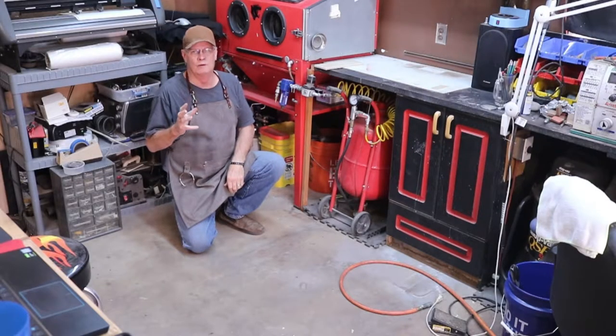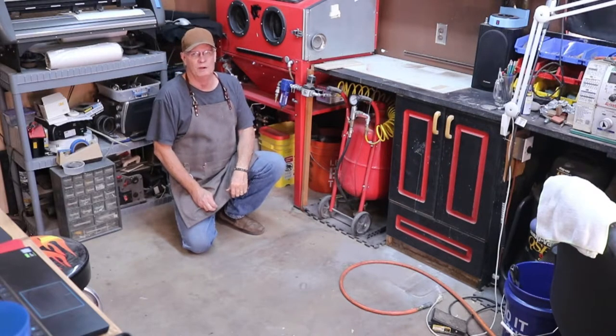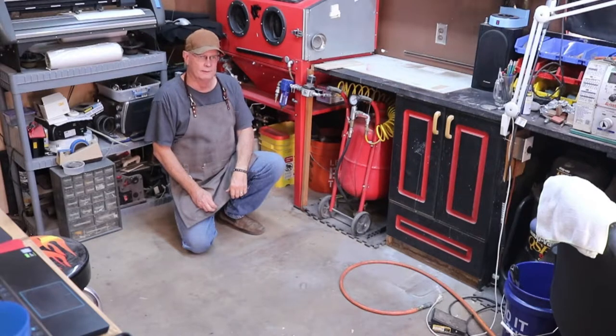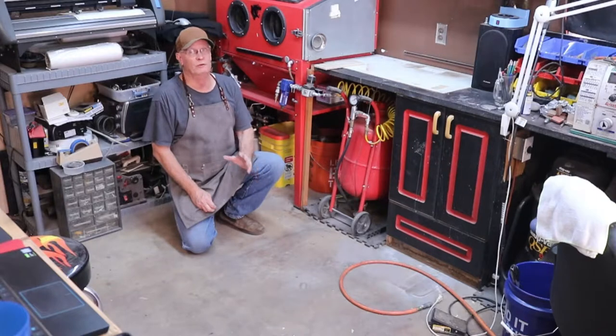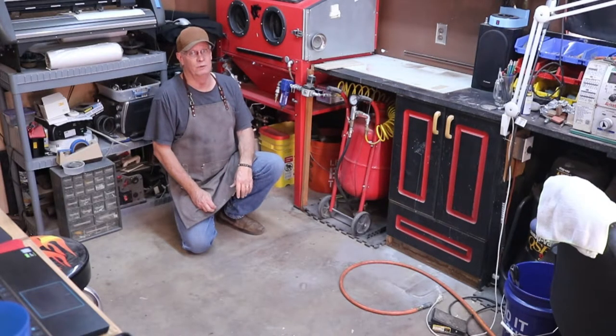At the heart of all of this is the 40-pound pressure pot. I'm currently running 180-grit aluminum oxide. I tend to like that a little bit better for the rocks versus the silicon carbide. I have both, but the silicon carbide is really good for glass. As far as the rocks are concerned, I'm sticking with the aluminum oxide.